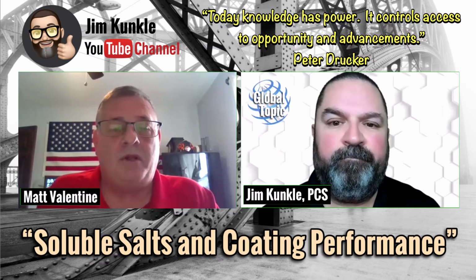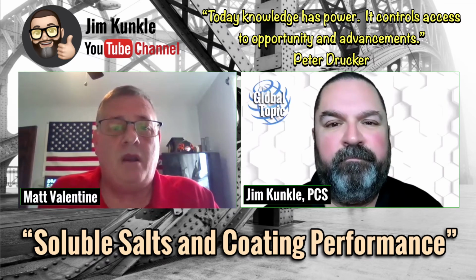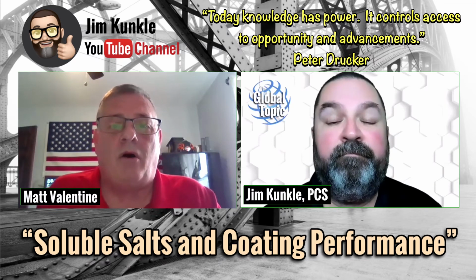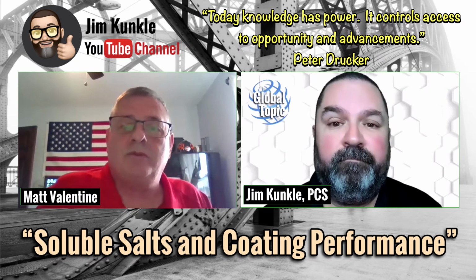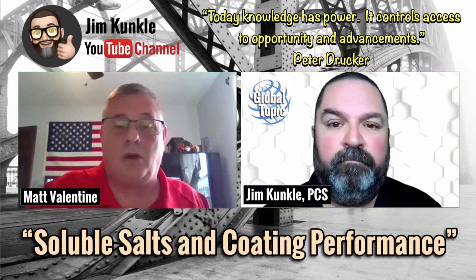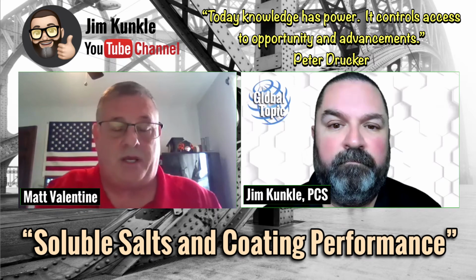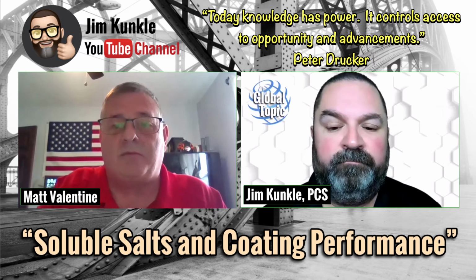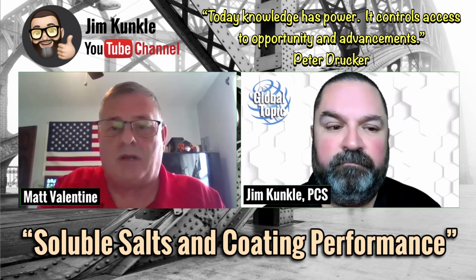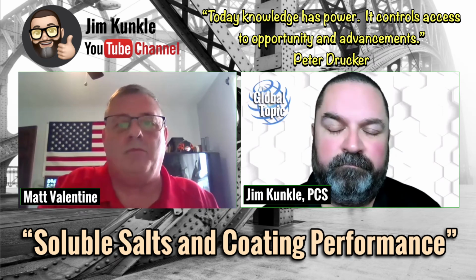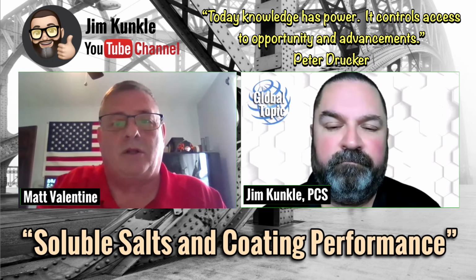And he determined that just 1 ppm of salt on the substrate has the potential to reduce the coating life of the system by 50%. We had some pictures. I don't know if you've got them there. You can put them up. It's the chloride limited impact.